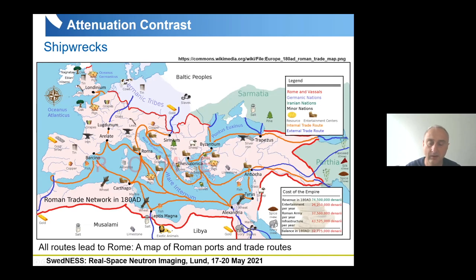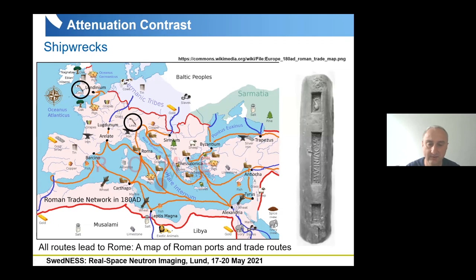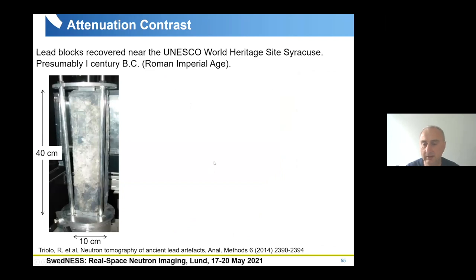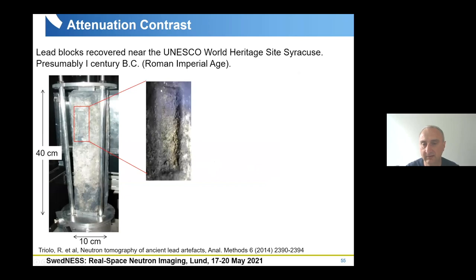The next application is to investigate some lead ingots, which come from Roman times, from shipwrecks which sank around Syracuse. It was interesting to find out where these ingots are coming from. This was the way of transporting lead material in Roman times with ships from the areas where it was gained. And the good thing is that all these ingots were stamped with the name of the manufacturer so that we can backtrace the area where it comes from. But after thousands of years in salt water, these ingots are completely corroded. We can see that there is some stamp here or area of stamping, but it's not really possible to read anything because there is a very thick corrosion layer.